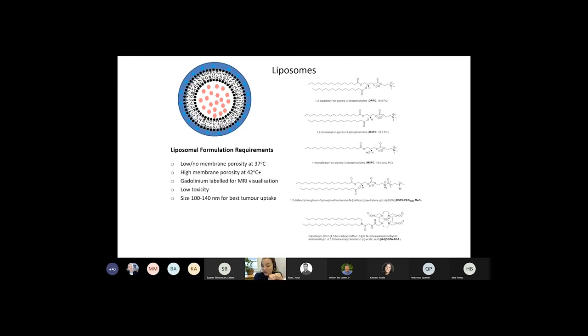The rest of the liposome is decomposed at that point, whereas below that temperature, below the 42 degrees, the liposomes are integer and intact, and they contain the drug without releasing it in the circulation. So in order to demonstrate that,